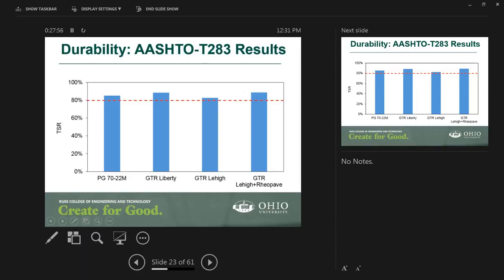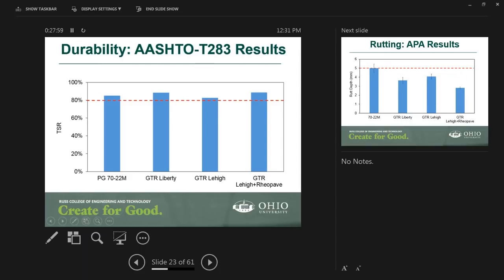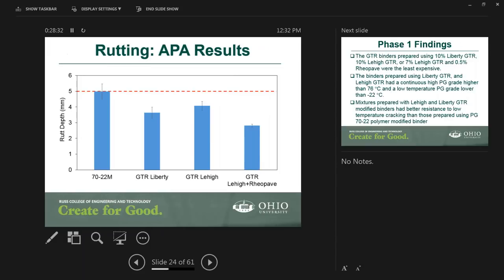And basically, we calculated the TSR, which is the tensile strength ratio, the ratio between the indirect tensile strength of the wet samples as compared to the dry samples. A minimum of 80% is recommended by most agencies, ODOT as well as other agencies. So that's the limit that I'm putting here. And in all cases, I would say that all mixtures, the GTR mixtures and the polymer modified, had a very similar TSR value, which was greater than the 0.8.